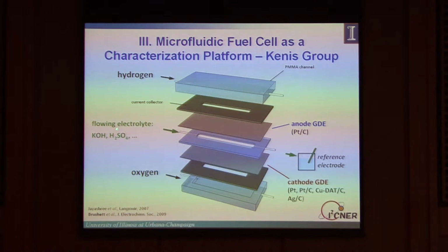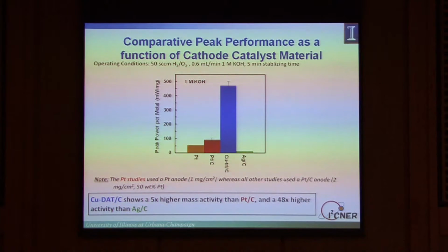So now what we can do is test these materials using a microfluidic platform developed by my colleague Paul Kenis. All right, he can do both the hydrogen side and the oxygen side simultaneously with a reference electrode. And he has tested our diaminotriazole catalyst. And what he has shown is that in base, this catalyst has about 5 times higher mass activity than platinum carbon material right here, and better than the more traditional silver carbon material that was used in, for example, the alkaline fuel cell in the Apollo situation.